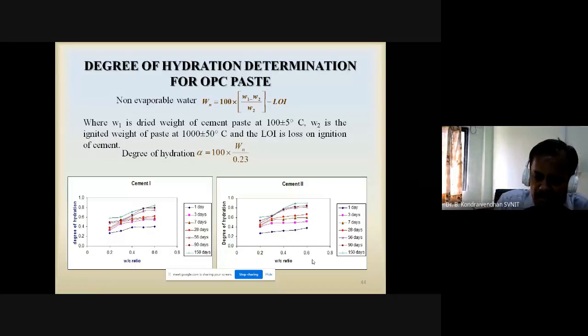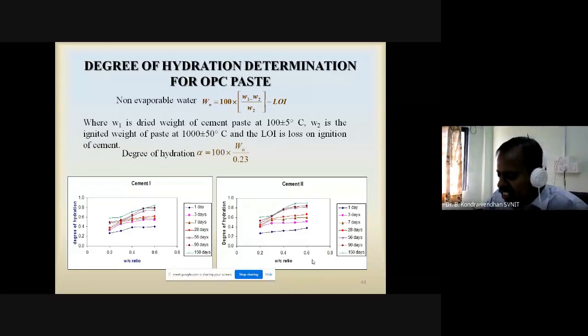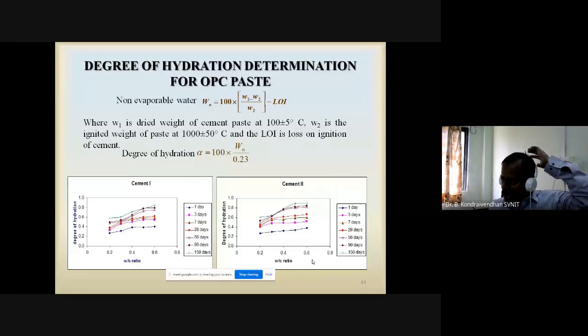Because according to T.C. Powers, 1 gram of cement has 0.23 gram of combined water, or chemically bound water. This is already available in the literature. In 1960, he revealed this and did extensive experiments, and came to know that 1 gram of cement has 0.23 gram of combined water. By using that concept, we can determine the non-evaporable water content. So we have done the experiment on cement paste for both coarser and finer cement, according to T.C. Powers.